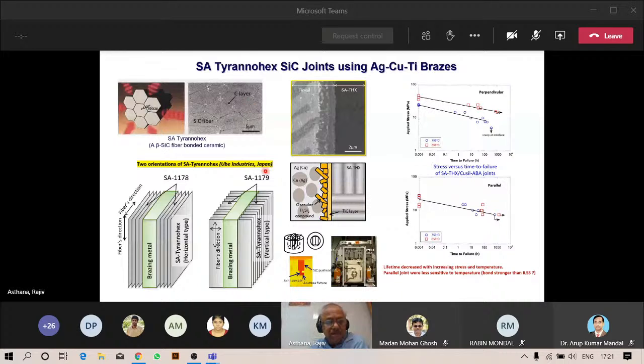These are the basal planes, and then you have the prismatic planes. We bonded this material on both faces. So in some systems, we bonded the basal planes using a braze, and in other cases, we bonded the prismatic planes. So we had two different orientations of the fibers at the mating interface here, and we did some studies on the interaction, phase formation, and all of that. We did not really find any difference in the chemical interaction. With the fibers oriented differently, in all cases we saw titanium silicide and titanium carbide, which is what you expect on the basis of thermodynamics.